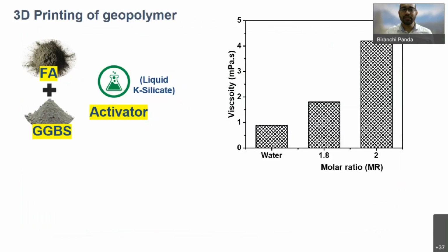Yeah, so if you investigate the material mix design, actually it contains again the same waste material like fly ash, slag, and instead of water we use an activator which is potassium silicate solution. So if you see the solution, it has higher viscosity than the water, and it depends again upon the concentration of the activator. If we are using a 1.8 molar ratio or activator concentration, then its viscosity is slightly higher than the water. And if you're going for a 2 molar ratio activator, its viscosity is again higher.